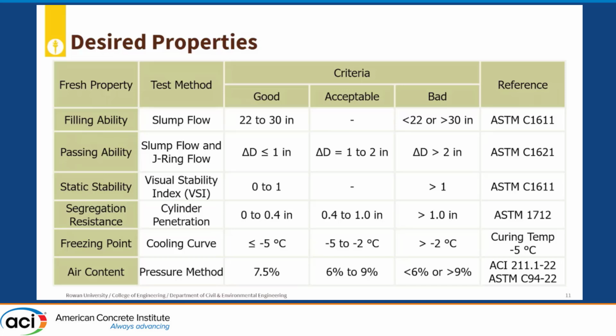Segregation resistance, we're using a cylinder penetration test, or the rapid cylinder penetration test. I have a picture in the next slide. Acceptable penetration for the cylinder is up to 1 inch. If you have more penetration, then you have less segregation resistance. Air content, our target is between 6% and 9%.